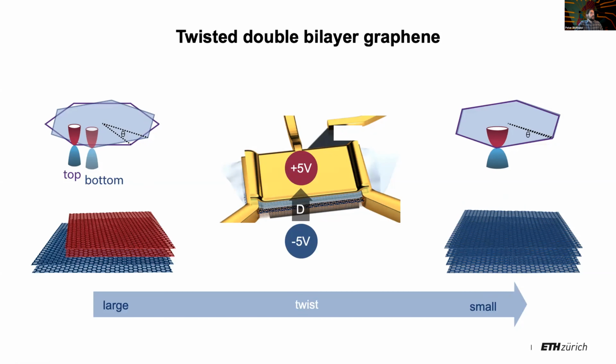So this band structure looks like the band structure of bilayer graphene. The main difference is that the energy scale here is much, much smaller. So we're on the order of 200 meV. That's also much larger actually than the bandwidth that you get at the magic twist angles where the bands are extremely flat. So this band is not very flat, but it's somewhere in between.